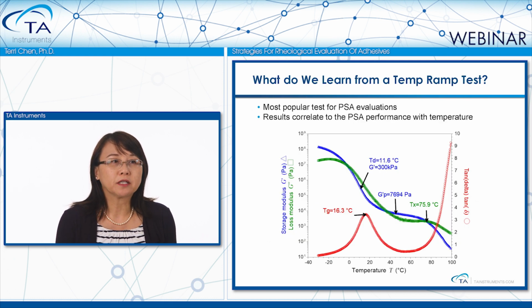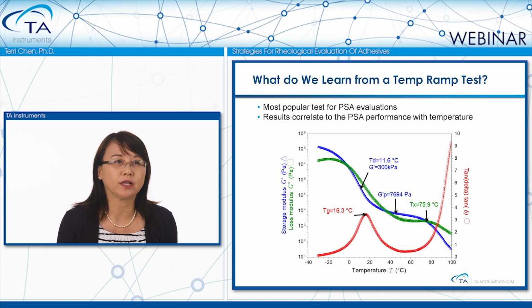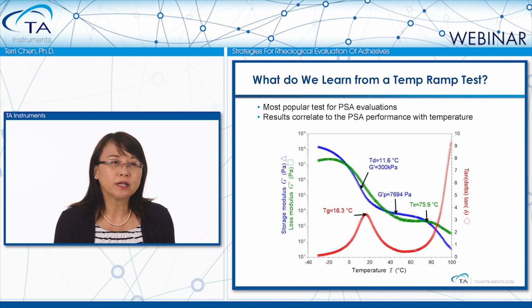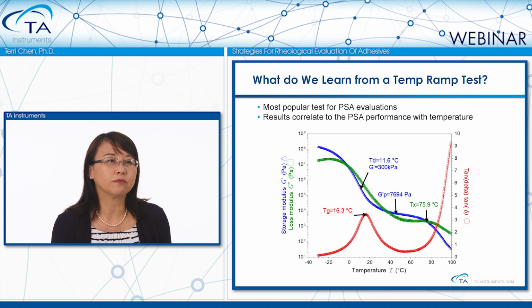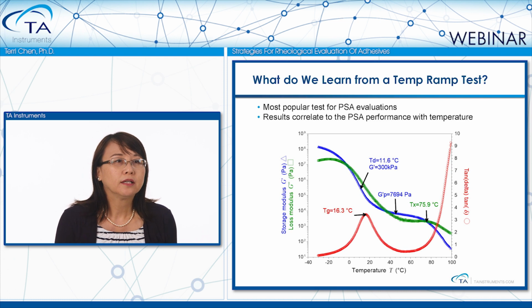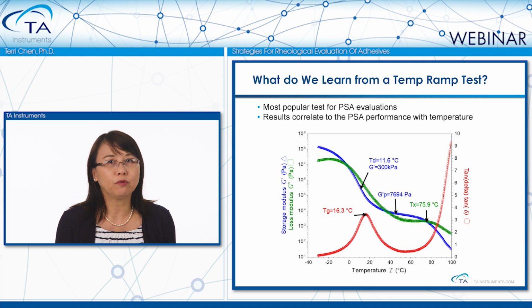Dynamic temperature ramp experiment is probably the most popular test in adhesive evaluations. This figure shows an example of a non-cross-linked pressure-sensitive adhesive temperature ramp result. This test provides much information on the performance of this adhesive. First of all, glass transition, Tg, is observed at 16.3 degrees based on the location of the tan delta peak.